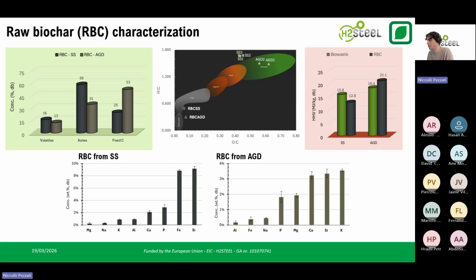And also here I reported the characterization, so the elemental profile of the two biochars. So focusing on the silicon, the phosphorus, the iron, particularly in the case of the treatment of the sewage sludge, we reach very high concentration levels. As you can see, silicon in the raw biochar from the sewage sludge is almost 10%, as well as iron. Phosphorus in both the raw biochars is instead around 2%. And this is important because we want to recover it later.